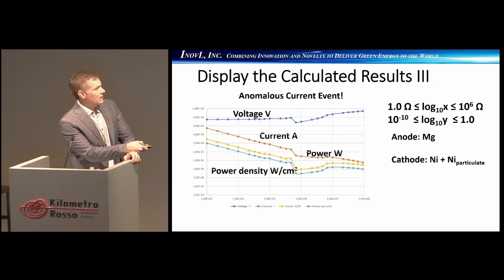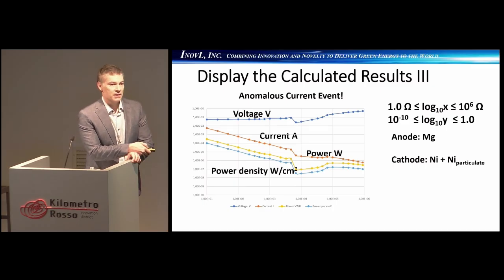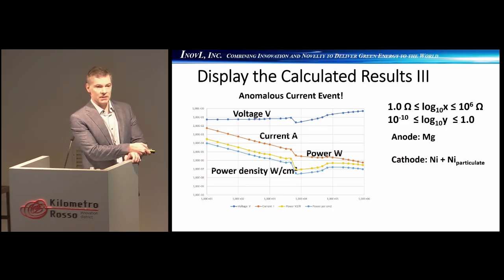All right, and here's a more interesting cell that we had. We were testing a cell, and this is a nickel cell where we're using a nickel particulate. And we hadn't really used a nickel particulate because all indications were that nickel needed to be hot. And so we had essentially avoided using that as something for co-deposition.